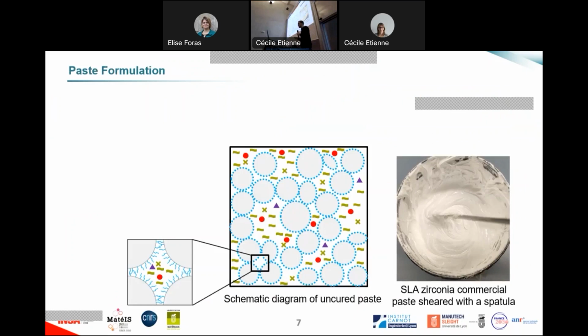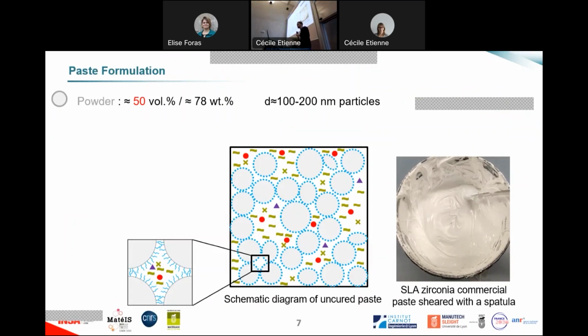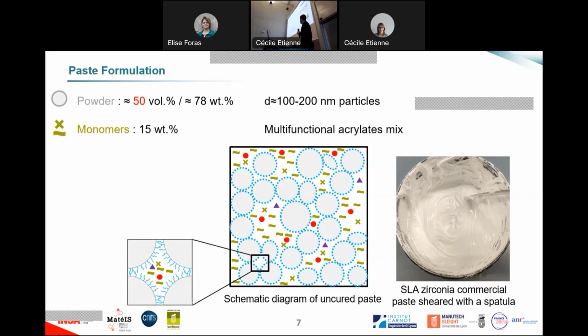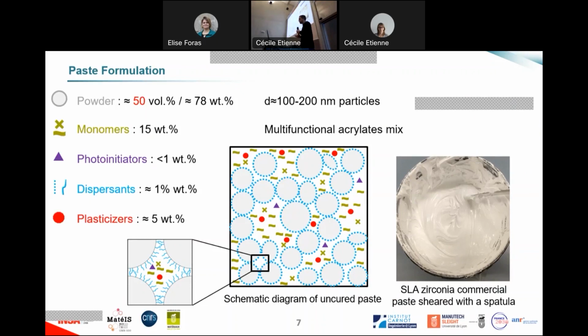So you can see a bit the laser, the pulse laser process for different shapes on a layer. And now talking about the paste, so you can see when we shear it, how it behaves, and a small schema that shows that we have here powder, so mainly powder, half of the volume. So small particles of zirconia for us to have small grains and good mechanical properties. We have monomers of acrylates that permit a fast polymerization, and this polymerization is permitted by photoinitiators. When they receive UV light by the laser, they will begin the polymerization. Then we have dispersants to make it flow well and achieve a good density, and also plasticizers to have a good thermal treatment when we debind, so when we remove the organics from the material. So at the end, we only have the powders that are linked together and that grow to make a full ceramic implant.